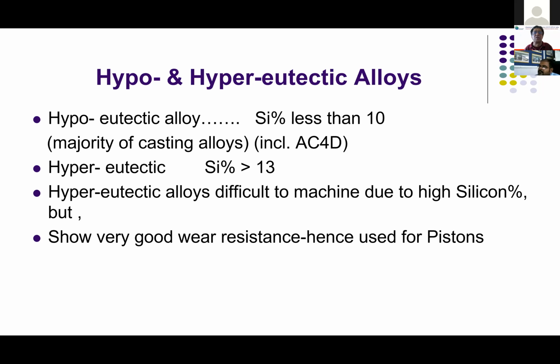When you are using a fully automated machine with very sophisticated tools, the silicon particles, being hard particles, will break the tool tip. The wear and tear of the tool at the time of machining will be very high. Therefore, any alloy maker should take care to see that silicon is dissolved completely. There are two things involved. If the silicon is not dissolved completely, it will keep floating on the surface and go into the oxide. You are paying money and buying silicon, and while alloying, if you lose some quantity, it is no use. To achieve 12%, or say 11.5%, you add 0.5% more, and then you are losing money.